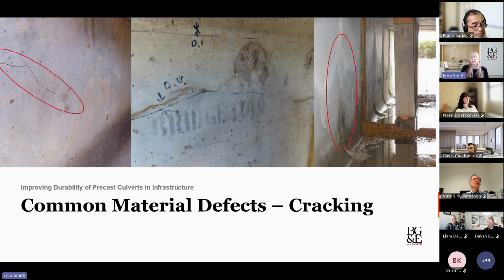So cracking - everyone recognises that reinforced concrete cracks, and there will be some cracking, but it's those cracks that are bigger than hairline that matter. Hairline is considered less than or equal to 0.1 millimetre. They may be considered harmless structurally, but we still need to look at those because they may open up and progressively spread to longer and wider cracks and then become a durability issue.